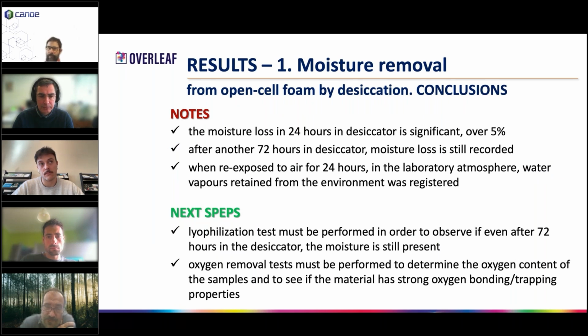As a short conclusion for this step, it can be seen that moisture loss in 24 hours is significant. It's close to 5%, which means the samples that we investigated were not soaked with water, but have a large content of water. After 72 hours in desiccator, the moisture was still recorded, and when re-exposed to lab atmosphere for 24 hours, the samples were capable of trapping water from the environment.